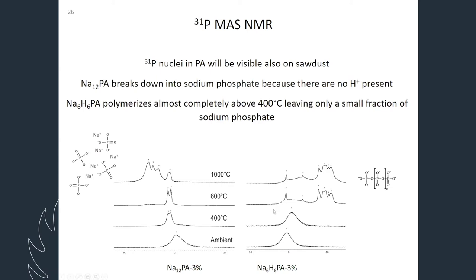But on the other part of the spectrum where we have 6 sodium and 6 hydrogen, then the peaks shift to the right instead. And those signals to the right, they tell us that we have polymerized the sample. And there is just a tiny, tiny fraction of sodium phosphate. So in principle, all of the phytate has polymerized into polyphosphates. So we need hydrogens there to get this polymerization reaction going.